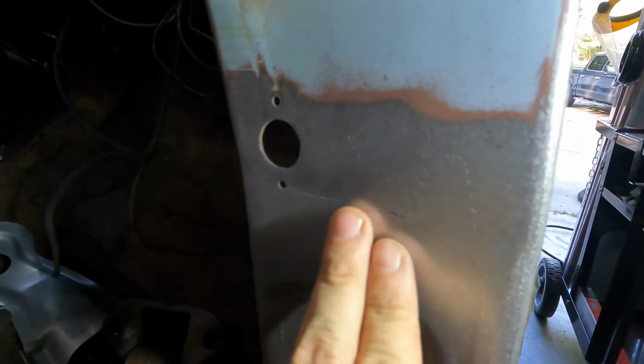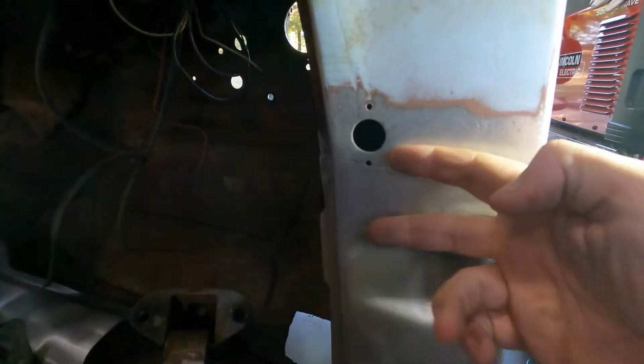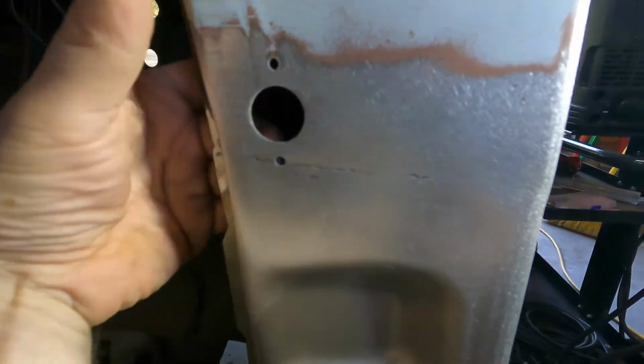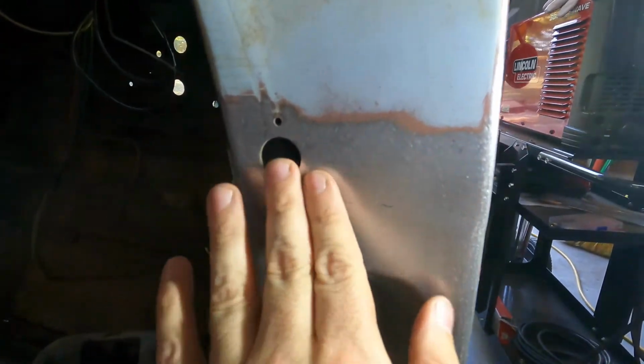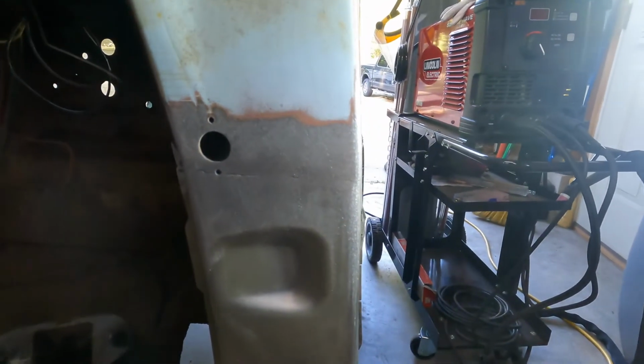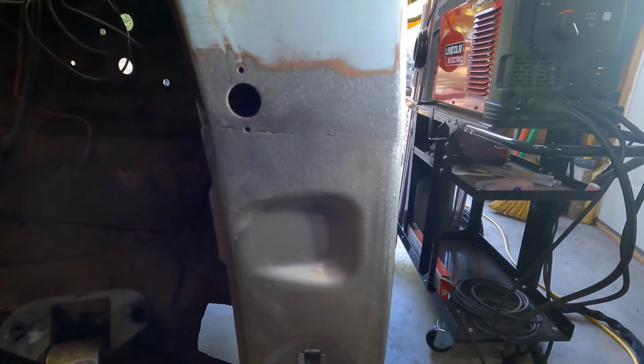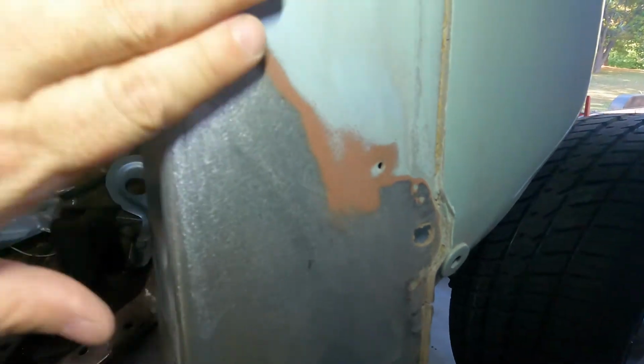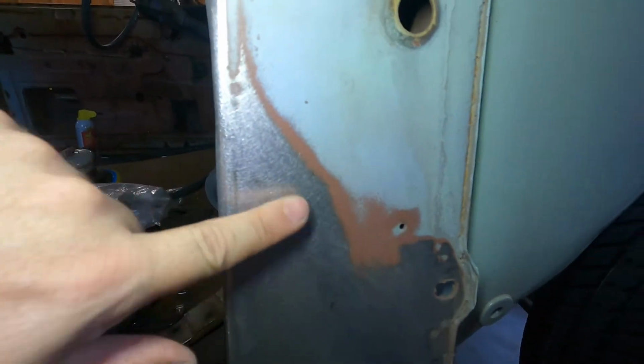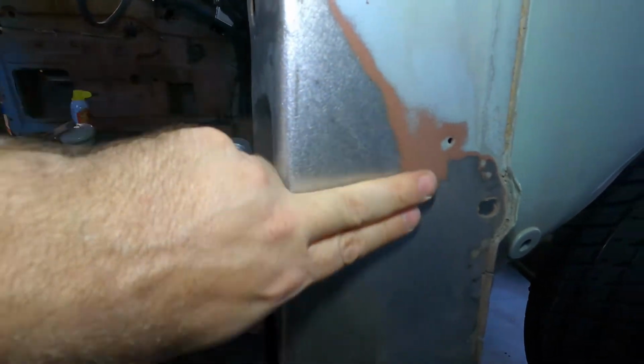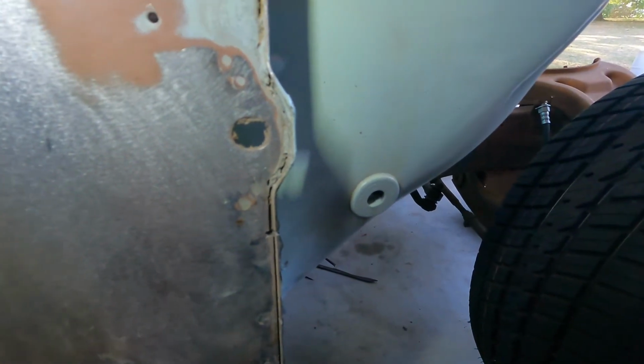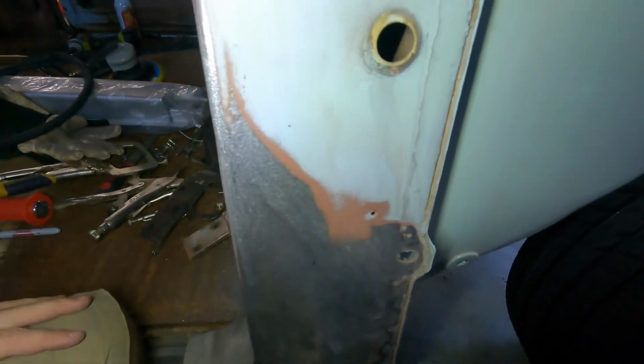Well, here's the almost finished product. Got a little bit of the weld edge here left to take care of, but what happened is this metal sunk in at this point, so I'm going to have to get in there with my hammer from the back side with the dolly on the front to push that back out before I can dress this down. You don't want to just sit there and dig it to make it hide, because your metal will get really thin at that point and it'll put a lot of heat in to do that. But this front side, in this spot about right here, it kind of bulged out, so I just hammer and dolly that back flush, and it looks pretty good. Blends in real nice. I'm pretty happy with that.